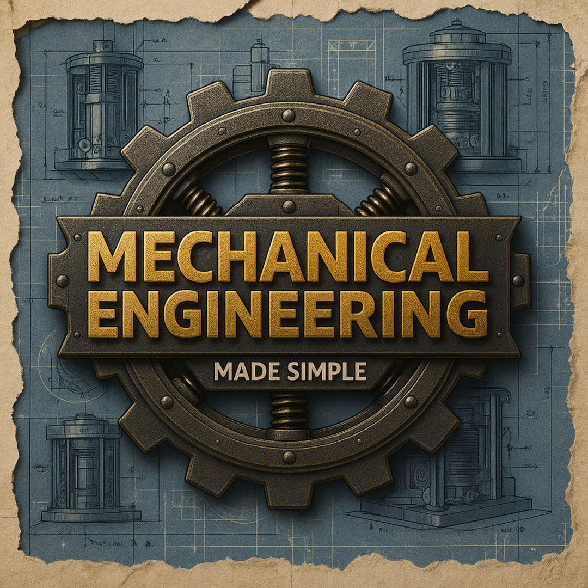Exactly. And then there's centrifugal casting, which just sounds like something out of a sci-fi movie. It's one of my favorites. It's a brilliant mechanical solution to a chemical problem. You basically pour the liquid metal into a cylindrical mold that is spinning at incredibly high speeds. Like a centrifuge. Exactly. The centrifugal force throws the dense, heavy, pure liquid metal aggressively against the outer walls of the mold. Meanwhile, any trapped gases, oxides, or lighter slag impurities are physically forced to float to the inner diameter of the cylinder. So you are basically spinning the trash right out of the metal. That's exactly what you're doing.